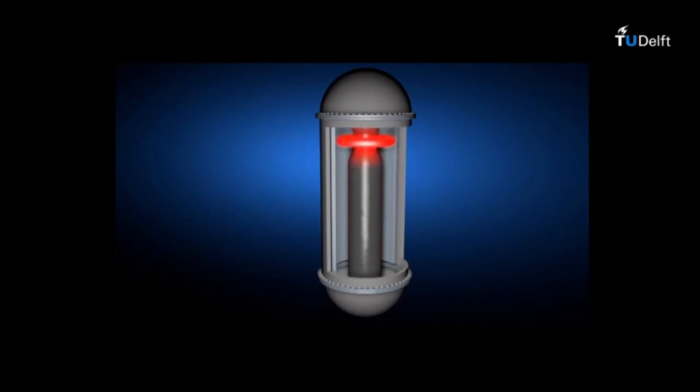The advantage of the float zone technique is that the molten silicon is not in contact with other materials like quartz, as in the Czochralski method. In the float zone process, the molten silicon is only in contact with the inert gas like argon. The silicon can be doped by adding doping gases like diborane and phosphine to the inert gas to get p-doped and n-doped silicon respectively. The diameter of a float zone ingot is generally not larger than 150 mm, as the size is limited by the surface tensions during the growth.